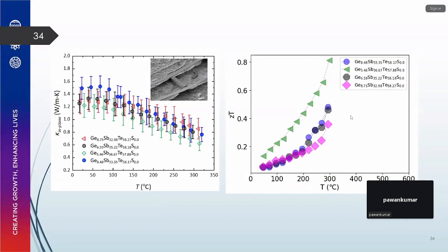We measured thermal conductivity using the bridge method from the Sunni group. They helped us measure, so we chose only 4 samples which show the highest power factor. Using the bridge method, the thermal conductivity is quite a bit lower compared to the bulk samples. Generally, germanium telluride is about 4 to 8 at room temperature. We're reaching around 1.4, and it drops with increasing temperature. At high temperature, 300 degrees Celsius, we're reaching about 0.6 to 0.8. We convert that to ZT, and the ZT we have achieved is 0.8, which is half of the bulk sample at this temperature.